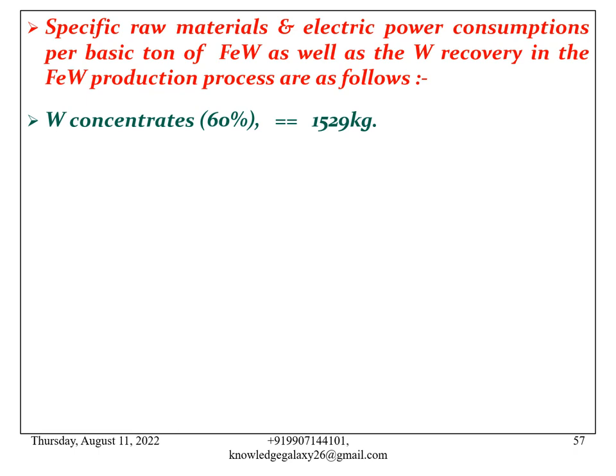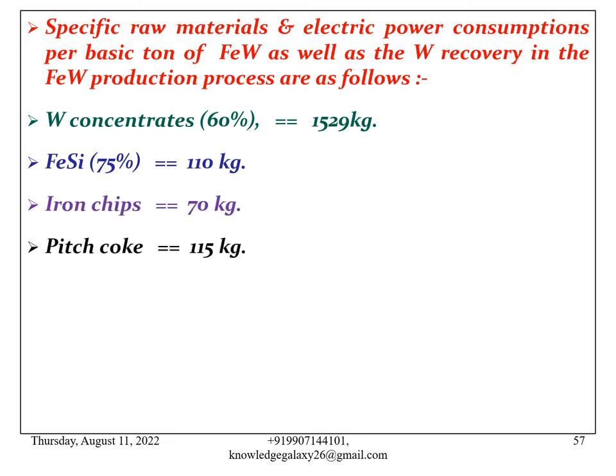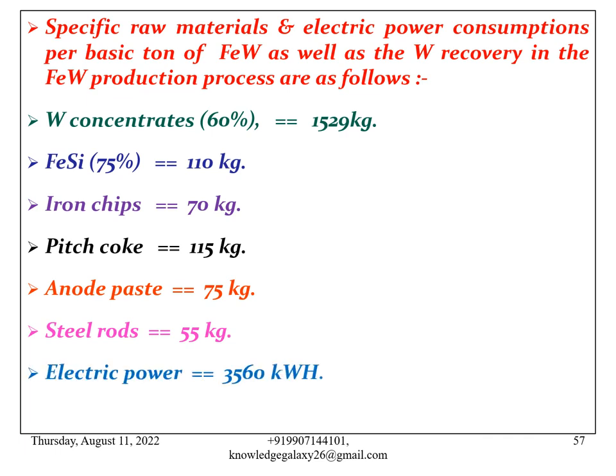First, tungsten concentrates required, 60% minimum, is 1529 kg. Ferrosilicon 75% is 110 kg. Iron chips 70 kg. Pitch coke 115 kg. Anode paste 75 kg. Steel rods 55 kg. Electric power required is 3560 kWh. And tungsten recovery is 99%.